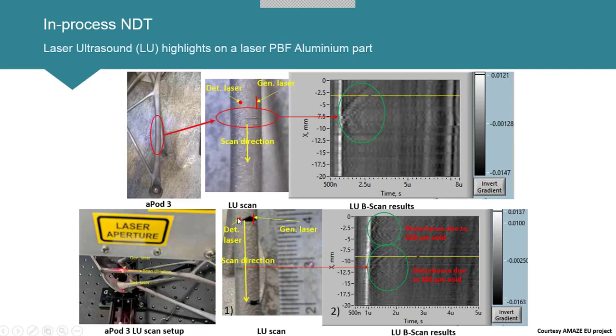So we have the same setup here, and both lasers were scanned in this direction, and this is the corresponding B scan. These dimensions are not from the laser ultrasound, but from X-ray CT. There were a couple of voids. In this case, it was about 200 microns, and I say about because obviously our system is not perfectly calibrated, but those are just ballpark values. But we can see this disturbance of the ultrasound signal in both cases. So it's showing capability for that.